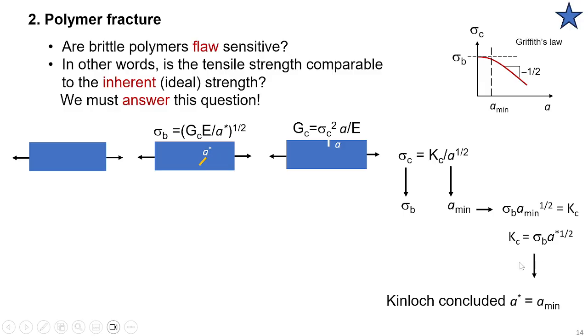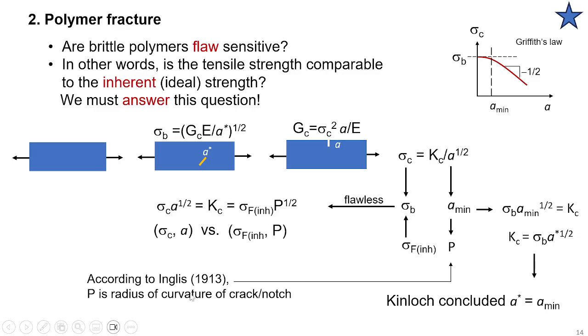In the textbook, if you analyze this, with simple math, you will be able to conclude that the reason there is a minimum crack size is because that minimum crack size matches the flaw size. And it turns out that that conclusion is highly problematic. It turns out the meaning of this minimum crack size has a different origin. I'm trying not to go into any details, but there are later analyses. You'll find that the existence of this minimum size is actually related to how sharp that crack is.